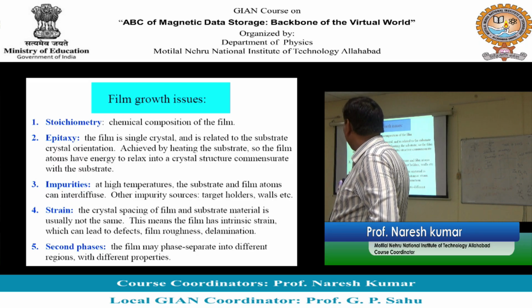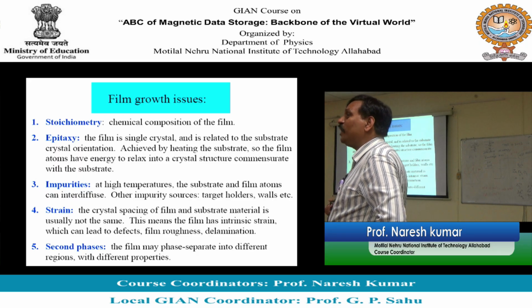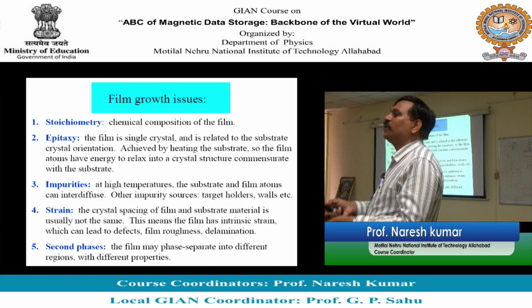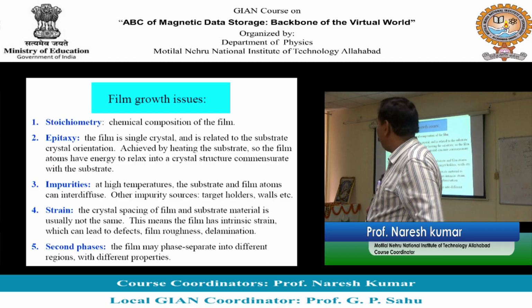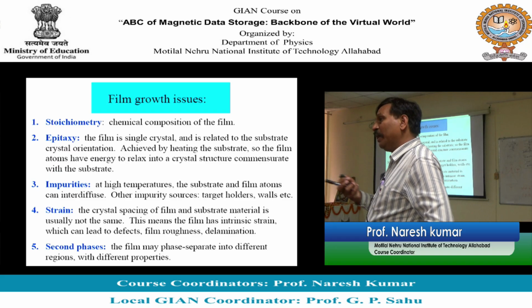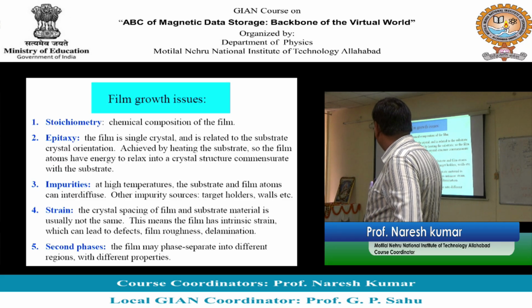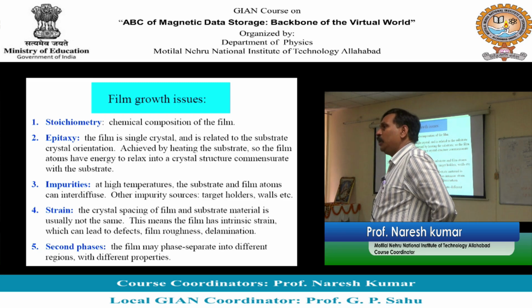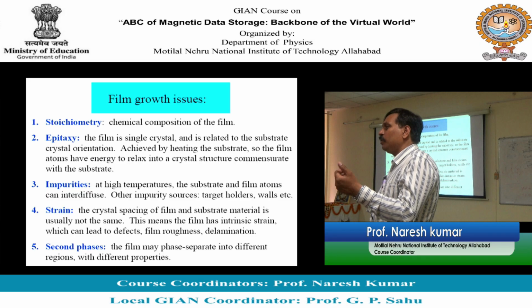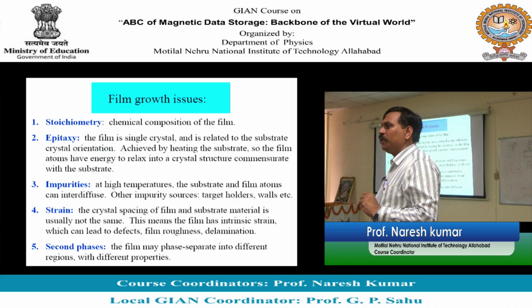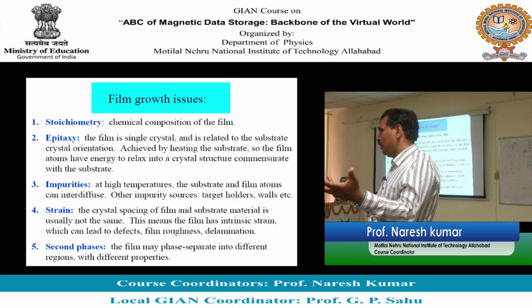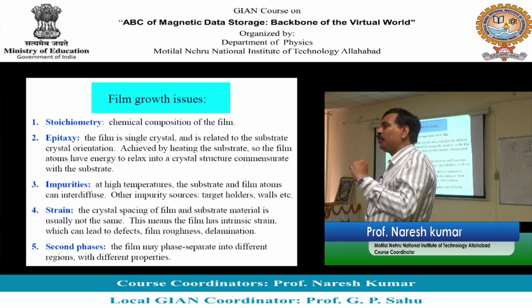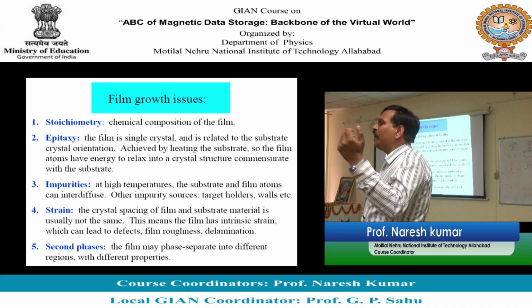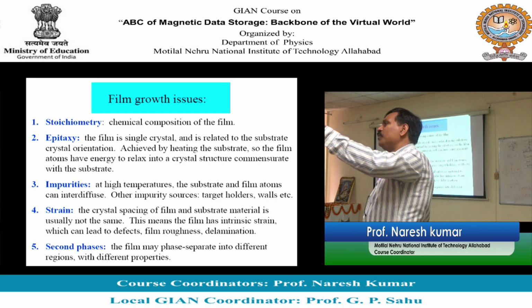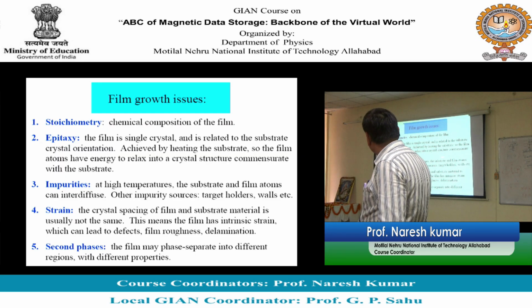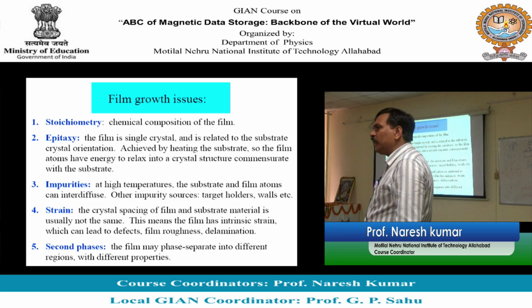Epitaxy, yes. If you want to grow an epitaxial film, epitaxial means a film of the same crystal orientation as that of the substrate. So growing films with epitaxial growth may be an issue. One has to choose the method and the substrate accordingly or wisely. Impurity, yes. If you are growing films at high temperature, suppose I am trying to grow a film on glass at, let's say, 400 or 450 degrees. At that temperature, it is quite possible that glass can diffuse into the film. If you are trying to grow films on a quartz substrate at 900 degrees centigrade, it is possible that quartz can diffuse into silicon, can diffuse into the film. And there may be some other impurities that may get in, maybe because of the atmosphere. So this is one issue.